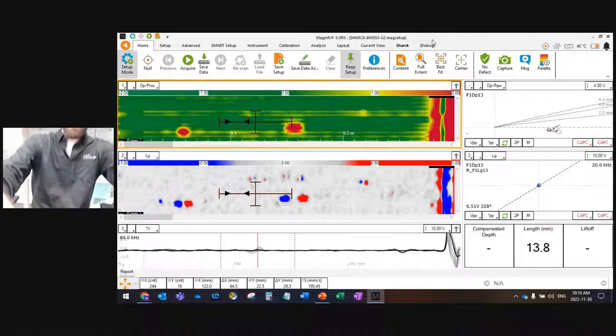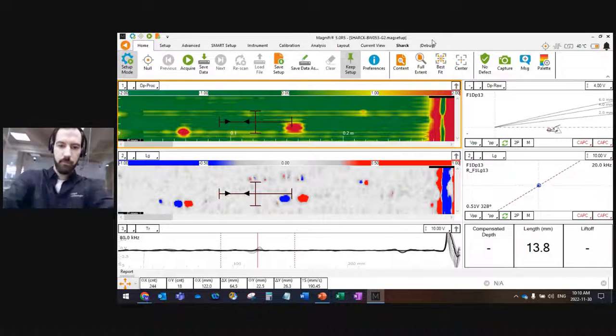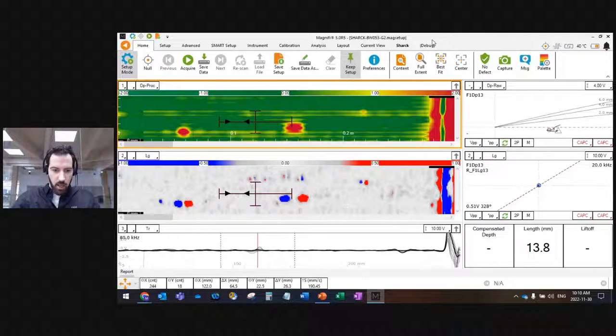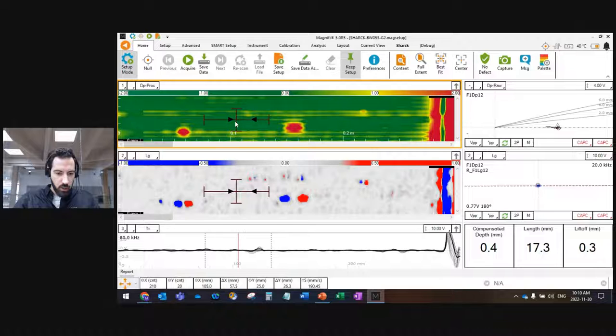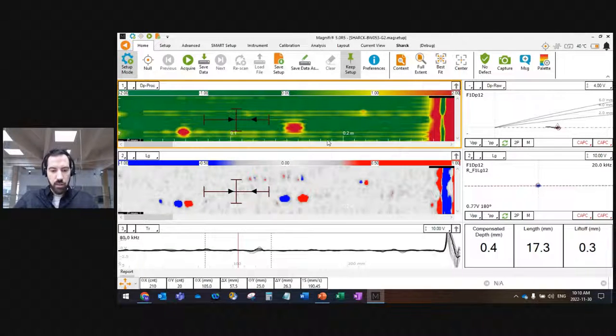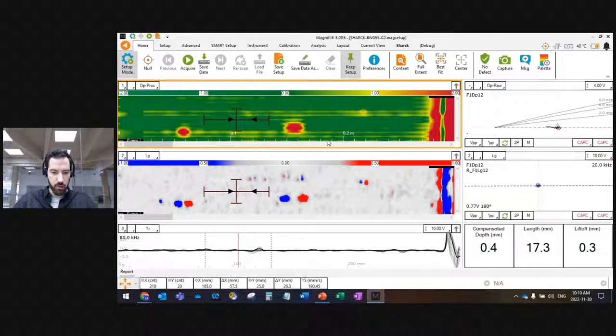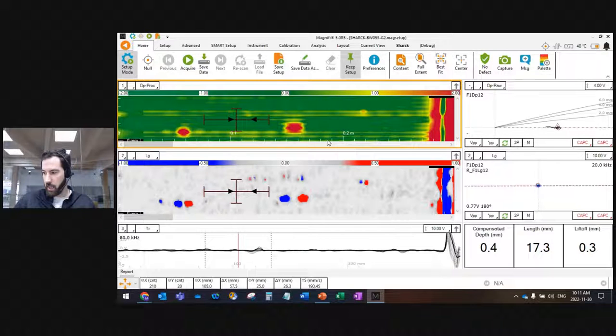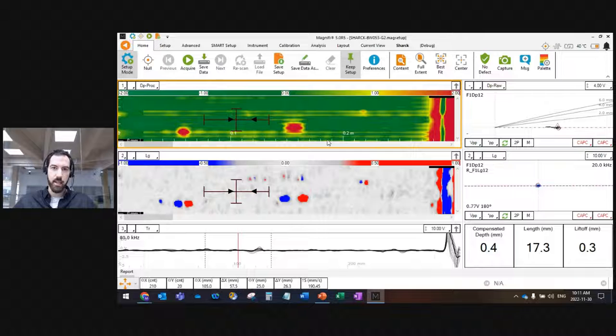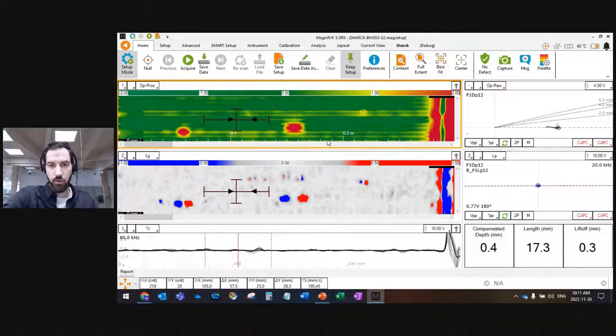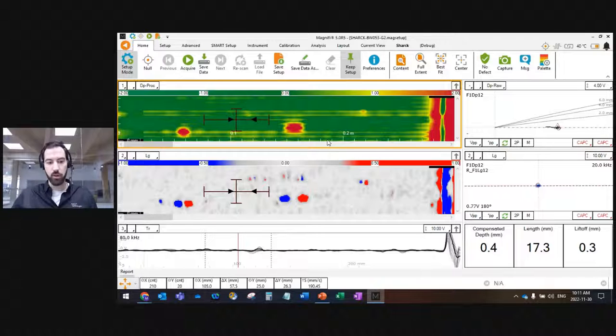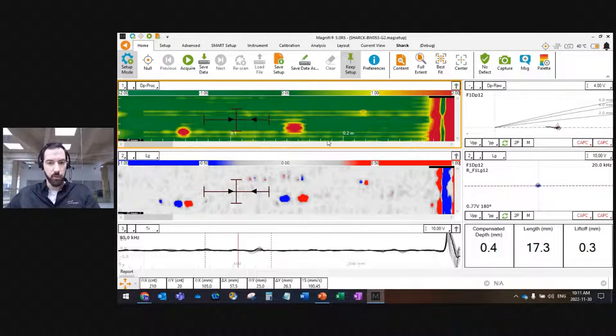So you can see already on the screen that you have some, it's quite obvious where the flaws are located, but you still have some of this background noise that you see on the screen. The reason for this background noise is what I said, the fact that the magnetic permeability of carbon steel is never very stable. It changes always. It changes from one plate to another, but more importantly, it changes within a single scan. The permeability will change.